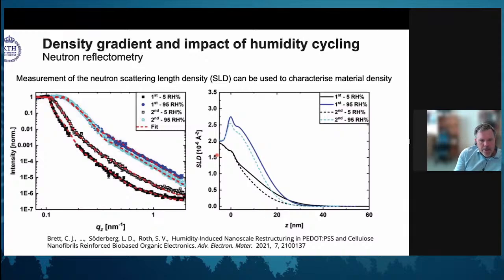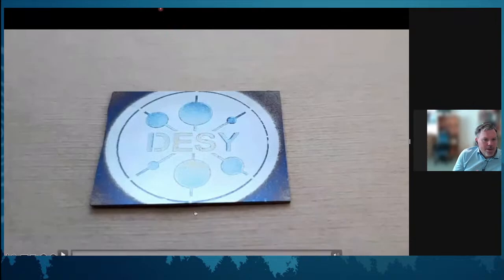I would say that these measurements typically took an hour to do for these samples. In reality, I want to show how fast the system can be. In this case, we have just sprayed a CNF film on a wafer, and a DESY sign has been used as an imprint. So here we have cellulose, and there is no cellulose here. It's just a mask for the spraying. So Kelvin did this, and now we will see what happens.